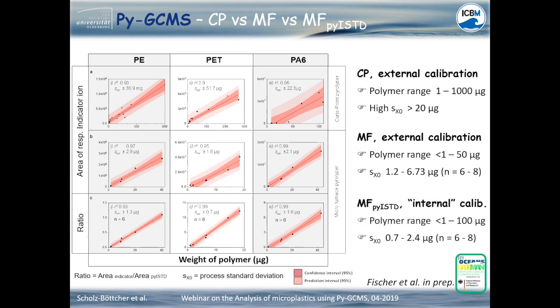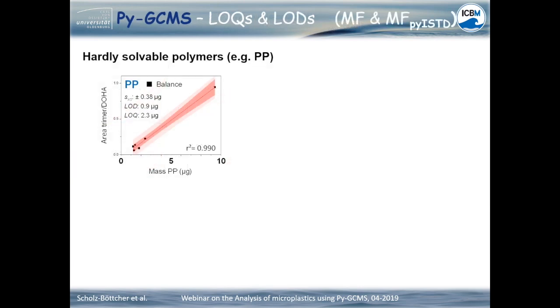The use of an internal pyrolysis standard further reduces the process standard deviation and enables quantification even much below 1 microgram on a semi-quantitative basis. The limit of quantification and of detection for this approach is highly restricted to the balance used.